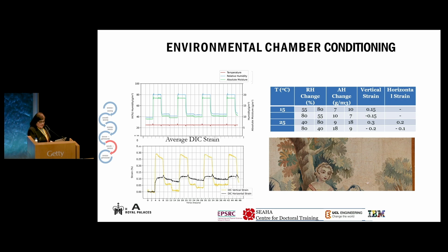So the changes in the strain the tapestry experienced between 15 degrees and 25 degrees temperature potentially could be interpreted by looking at the variations in absolute humidity. At 15 degrees, Pedro calculated that absolute humidity increases from 7 grams per cubic meter to around 10, while when the temperature is set to 25 degrees, it changes from around 9 grams per cubic meter to 18. So for the same levels of RH, when the temperature is higher, the air contains more moisture, and potentially the tapestry fibers absorb a higher amount of water, which causes more strain.